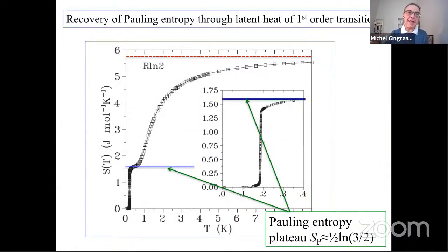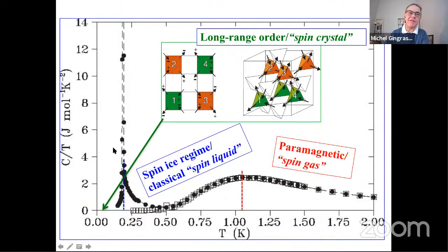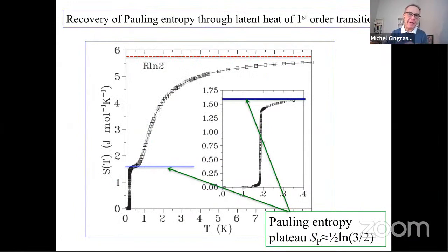This transition at low temperature is signaled by the peak in the specific heat, and it comes with a latent heat. It's a first order transition, and the latent heat at the transition is very, very close, as illustrated here by the inset, to Pauling's entropy. So all the Pauling entropy gets removed through this first order transition, and the ground state is unique. So one doesn't need quantum mechanics to restore the third law. It does it on its own because all these states are not exactly degenerate. They have slight differences in energy, but the system is somewhat frozen.